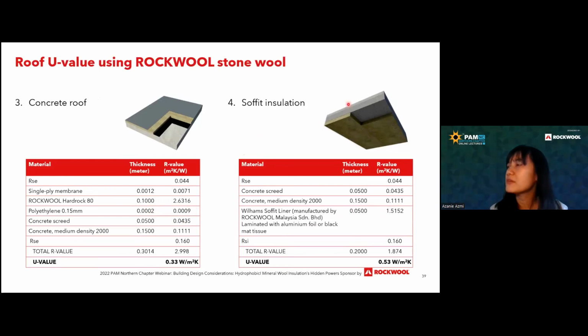Another thing is, I'm not sure whether you're familiar, we have these soffit insulations. What you do is you just put insulation underneath the concrete floor slab and you can already comply with 0.6. You need 50 mm and the installation is quite easy. What you need is just insulation pins. Let's say for one insulation 1.2 by 0.6 m, you need 5 pins, or sometimes they put 6 pins to help hold the insulation underneath the concrete slab. And with 50 mm, it already complies with that U-value performance.